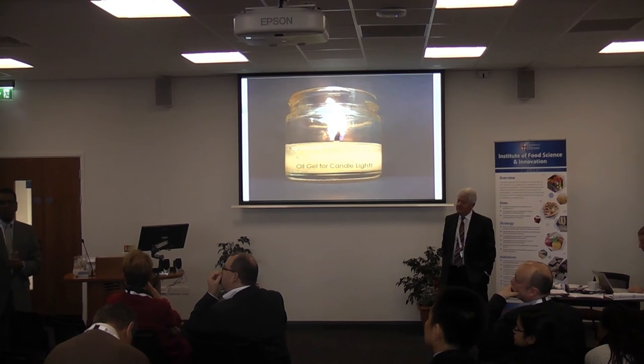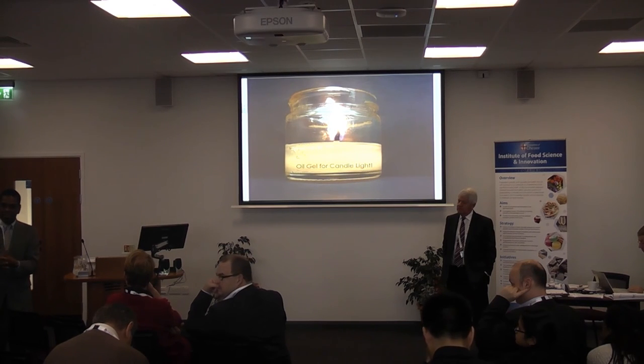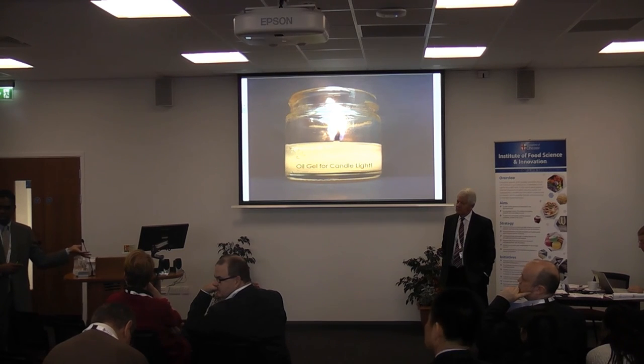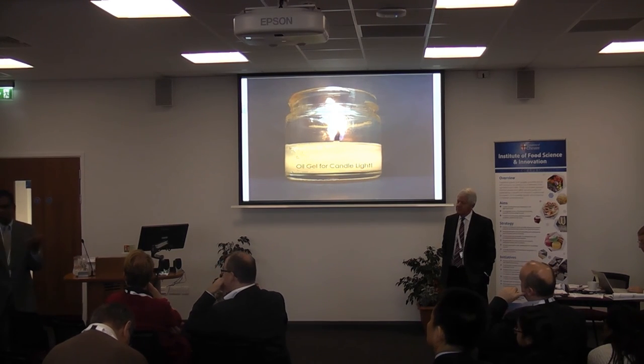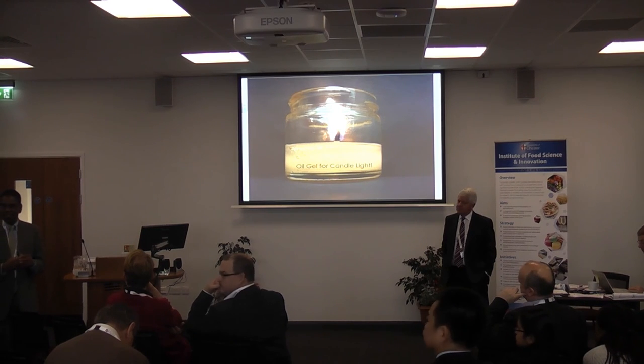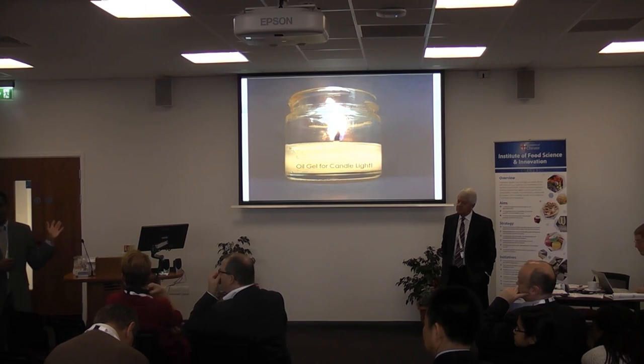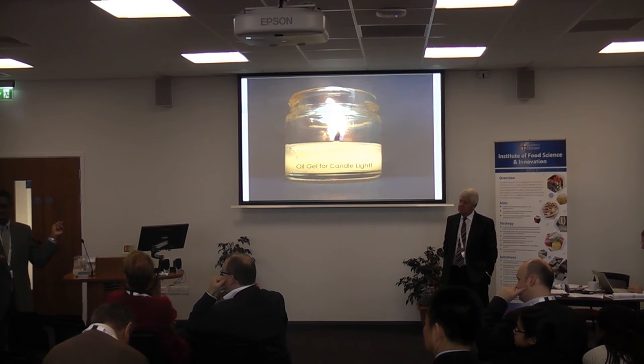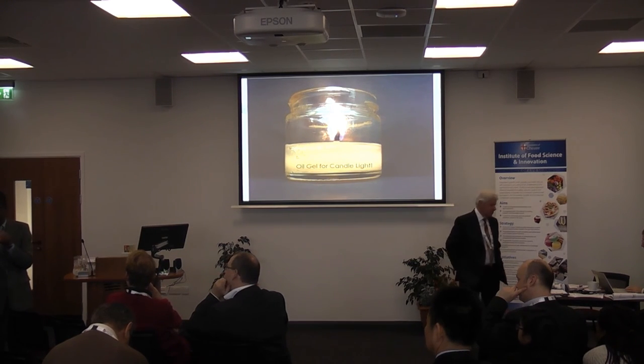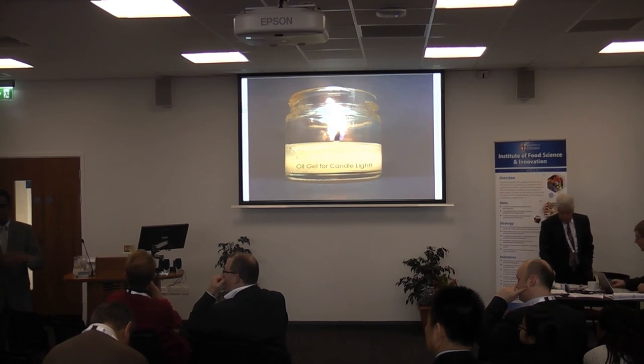But that is one kind of concern, because the polymeric gels can be much more mechanically robust and thermally robust. But that is the advantage here, we can make it reversible. But the usual temperature is above 50, 60 degrees centigrade. pH, these molecules are not responsive towards pH because these are neutral molecules. If you start with amino acid based gels, they are pH sensitive. But our molecules are not pH sensitive. We tested with different kinds of salts and nutraceuticals. It is still stable and it is robust.